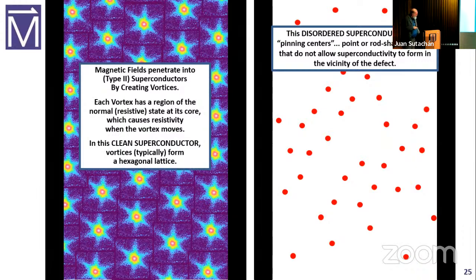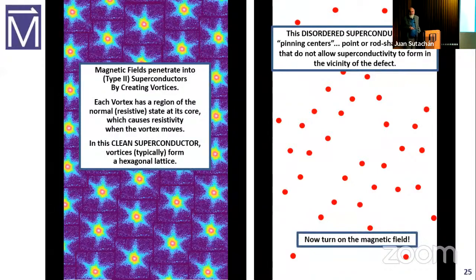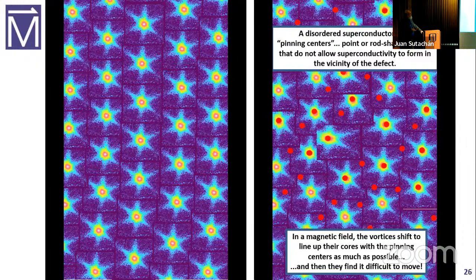So what happens when you turn on the magnetic field on a dirty superconductor that's been engineered by these genius engineers? Well, the hexagonal lattice distorts. The vortices shift because they want to line up their cores that are already not superconducting with the pinning centers that are already not superconducting, because then they don't waste any energy. And once they're stuck on that pinning center, they can't move. And what I didn't tell you yet is when a vortex moves, it kills superconductivity.